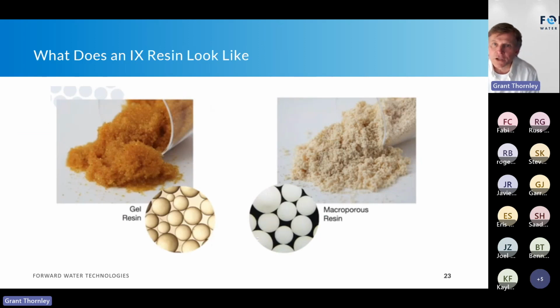So what does a resin look like? Ion exchange resins come as gel or macroporous. Those are the two most common. These are uniform, and you can see they're bead shaped. You can typically tell gel resins because they're kind of translucent. So if you ever mix up your resins and you're testing them, you don't know what's what, just remember that gel resins are translucent and macroporous resins are opaque. That's a quick way of differentiating what you're looking at if you're looking at two beakers of them.